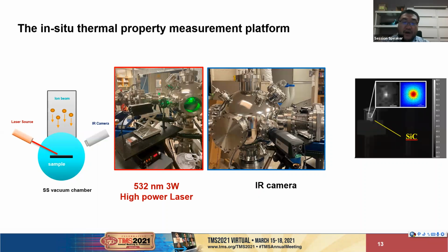Okay, this is the closed loop of the laser source and the IR camera. You can see what it looks like when you turn the laser on. It is a high power laser with a power of 3 watts, and the lens in between the laser and the chamber focuses the laser to a tiny spot on the surface of the sample. And on the other side, you can see the IR camera, and the left figure, the red figure, shows we have successfully demonstrated the temperature gradient on standard silicon carbide, and it validated this method, so we are able to get the temperature gradient from the laser hitting the sample.